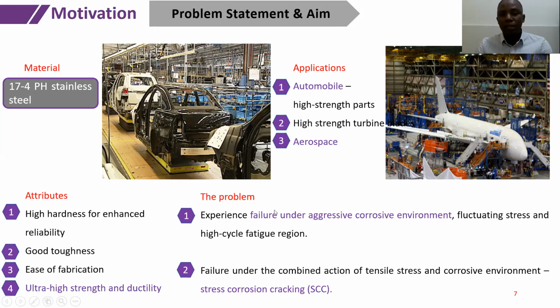However, there's a problem. The problem is that this material experiences failure under aggressive corrosive environments. And then when combined with some tensile stress and corrosive environment, this material also fails. And that is why we came up with this method to see if we can correct this problem, improve the properties of this material so that it can be fit for these companies and reduce the level of corrosion to the minimum. And it can serve as supply to most companies that we have around.